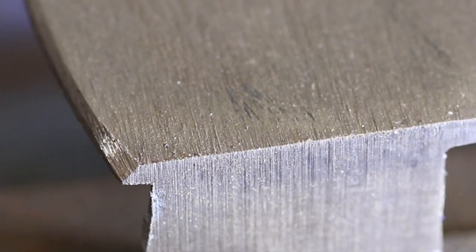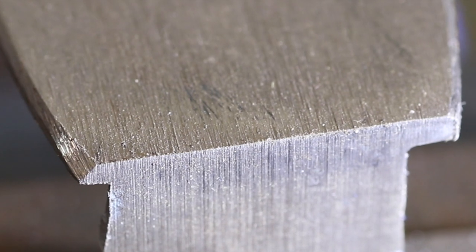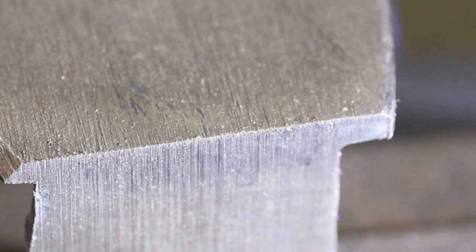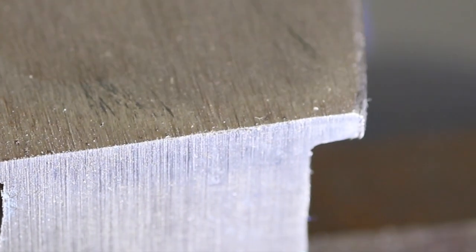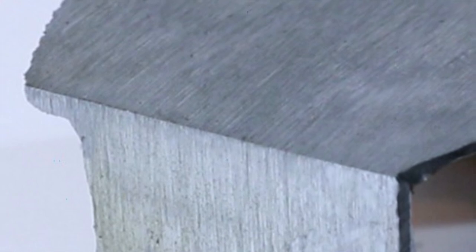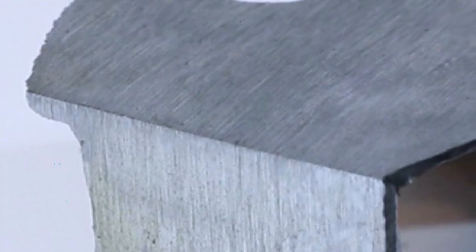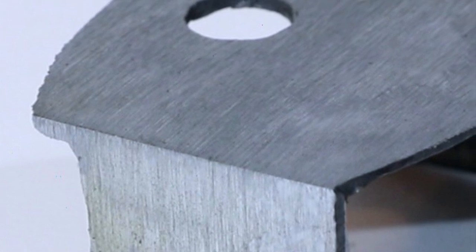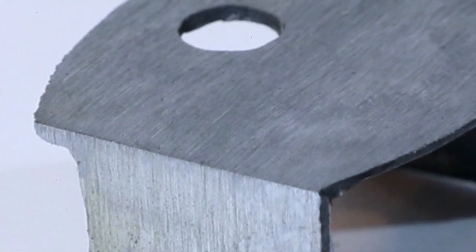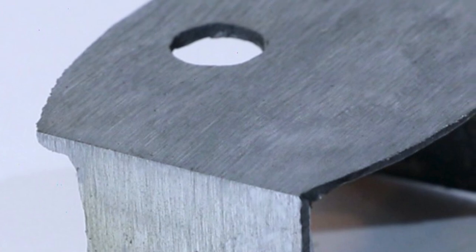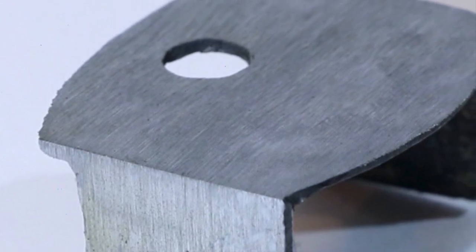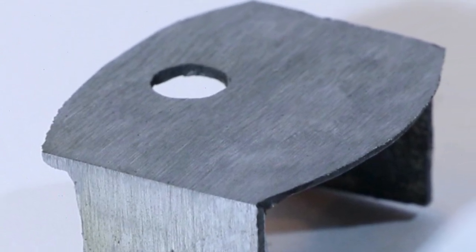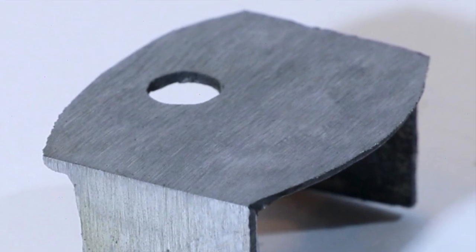So that's basically all there is to it. There's a little bit of setup which isn't really too complicated and then from there you just take your time, use light hammer blows, work from both sides evenly. The real key is to anneal often and keep that metal as soft as you can. Once you start to notice that the metal isn't moving as easily as it did the first couple of times that you hit it, stop what you're doing, throw it back in the fire, redo the setup and keep working. You'll save so much time by taking the time to anneal it often. You won't learn it until you break a few but trust me that's the key to the whole process.